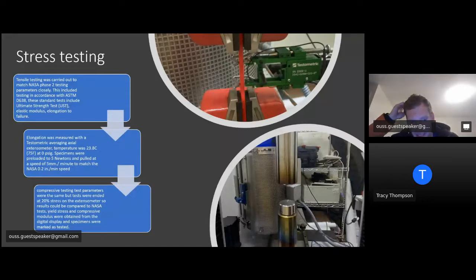Then I did the compressive tests. So I 3D printed the compressive samples, and then I tested those the same way. So the top picture there you can see is me using a stress tester at Harwell campus in the United Kingdom, and a very expensive machine. And the green item you can see there is the item that measured the elongation as it was on its way to failure. The bottom picture is the compressive stress test machine. It was excessive because the part I was trying to break was very small. So again, this measured at Harwell campus in the UK, and I got some very interesting results.